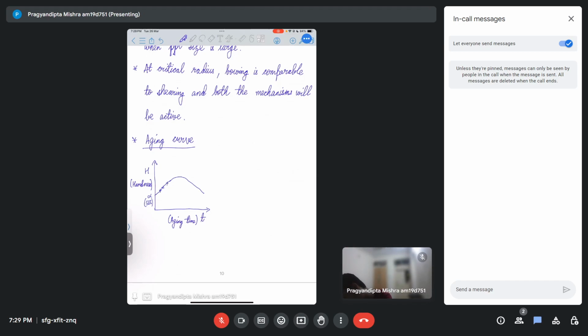So you'll have all these regions where GP zone is present, followed by theta double prime, which will be somewhere here. Okay. Then you will reach the maximum, after which you will have theta prime and finally theta. Actually, theta will be last. You can say something like this. This will be theta. This will be theta prime. So there are regions where you will see GP zones, theta double prime, theta prime, and finally you'll get theta. Okay.